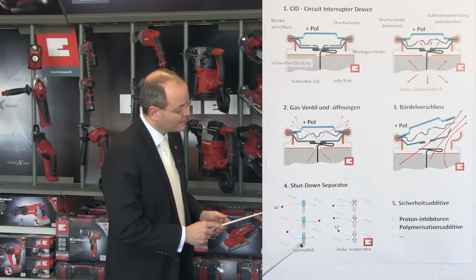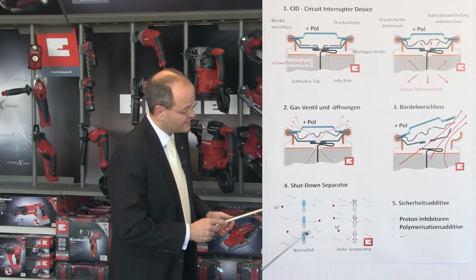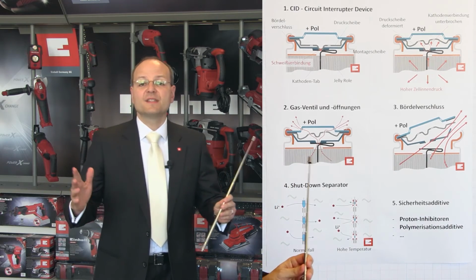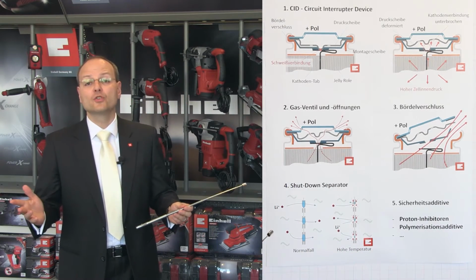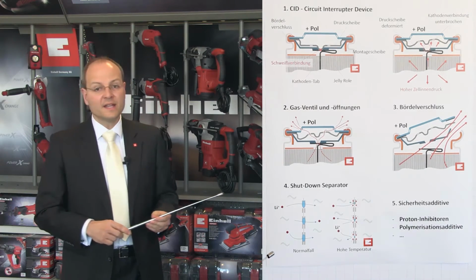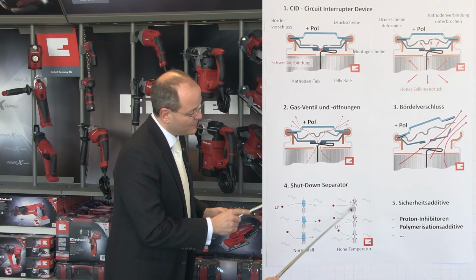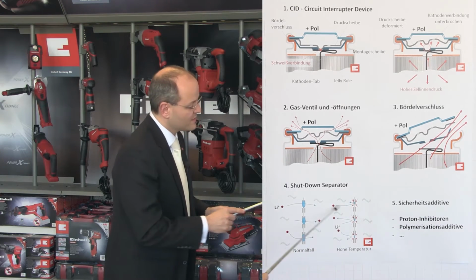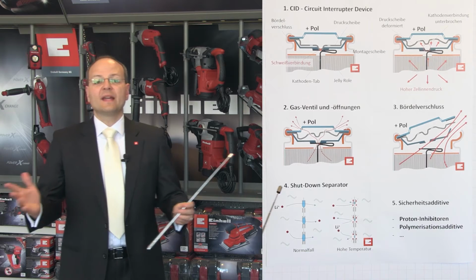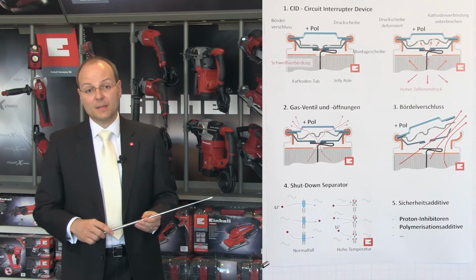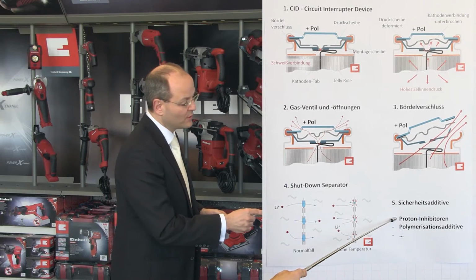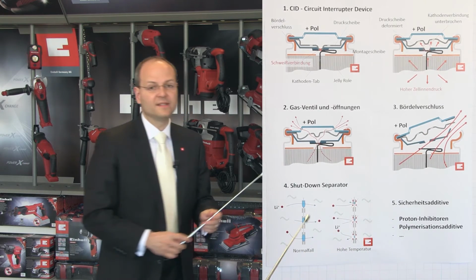The separator is one of the most critical elements in the cell. It must avoid internal short circuits in the cell. In the process, it has a thickness of just a few micrometers. Triple-layer polyolefin separators are used in the Power X-Change cells, which ensure ion conductivity with their microscopic pores. These pores play an active role in order to protect the separator and therefore the entire cell against thermal overloading, for example, excessively high temperatures. They melt and close the separator, as a result of which the flow of ions through the separator is interrupted. In addition to this, a number of additional cell stabilizing additives are used, for example, proton inhibitors and polymerization additives.